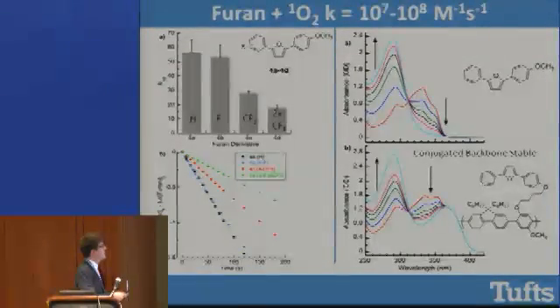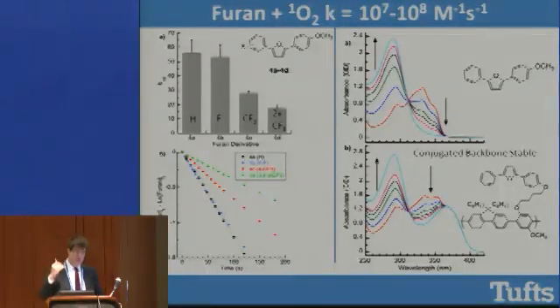You see a relatively nice isosbestic point and nice disappearance of the furan and appearance of oxidized products. Now what we're looking at here in the bottom right is the UV spectra of the polymer, this conjugated polymer which is going to be our fluorophore, with a furan attached. You can see south of about 360 nanometers, we see the same sort of response of the furan moiety to singlet oxygen here. North of about 370 nanometers, where only the polymer backbone absorbs, we see no degradation of absorbance, which is really important for us, especially since we're looking at a fluorescence quenching event. And so the conjugated backbone here is stable under our reaction conditions.